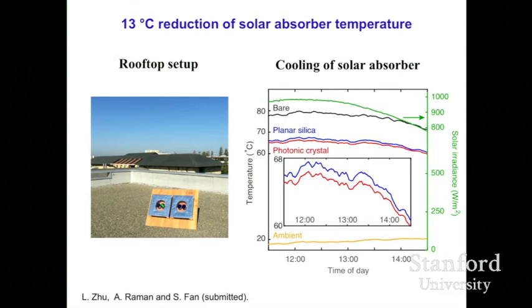So again, we perform a rooftop experiment to demonstrate the cooling performance. So in the first experiment, we basically take the same, very similar setup as we did with the daytime radiative cooling experiment. We put these wafers in. We cover each of these boxes here with low-density polyethylene to cut down the convection, and we measure the temperature under the sun. So you can see that by putting a silica layer on top, you have a significant temperature reduction as compared to the bare silicon wafer.